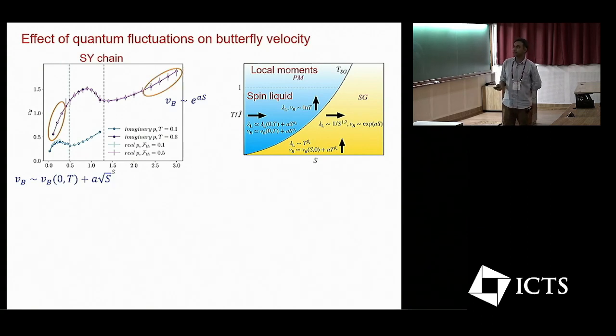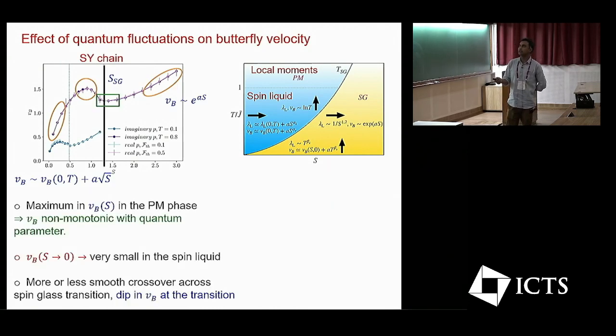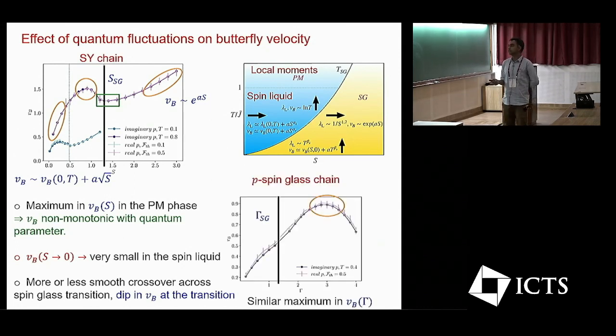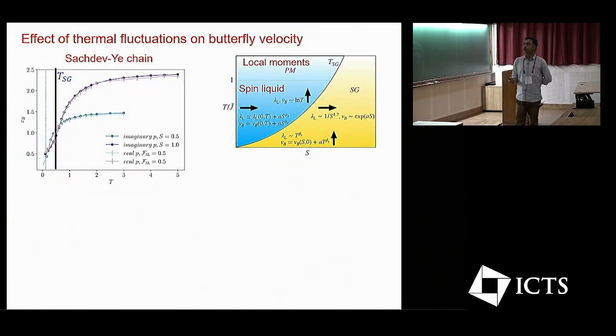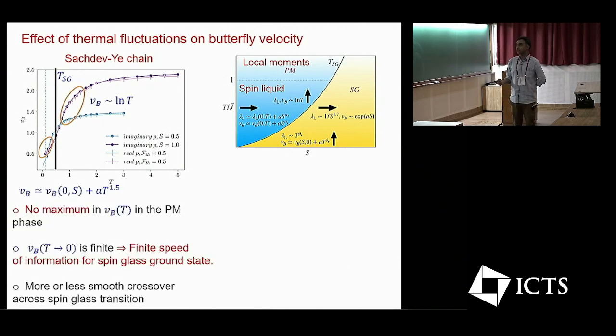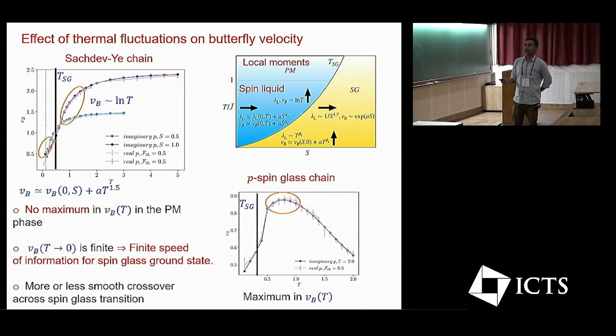There are some asymptotic behaviors that you can extract here, but the main point is you still see a maxima above the glass transition temperature, and probably you imagine that something is happening to the glassy complexity there. A similar feature you see in the p-spin glass model. Now, if you look at this as a function of temperature rather than spin, in the Sachdev-Ye chain, the Sachdev-Ye model, there is actually no maxima. Like I showed earlier for the p-spin glass, there was a maxima above the glass transition temperature, but here it doesn't appear.